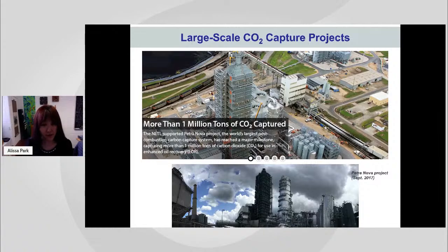And in fact, it is significant, because in the United States, power plant efficiency is very low to start with, about 34%, because the plants are relatively old. If you're reducing your power plant efficiency from 34 by even 1/3, now you're in the 20s. So this is becoming a challenge. If you want to make the same amount of electricity in these power plants, you basically need to burn 1/3 more fuel, which is not good either. But still, we thought it was a good idea to do it because carbon management is critical for our sustainable future. So one thing we started asking was why this requires so much energy.